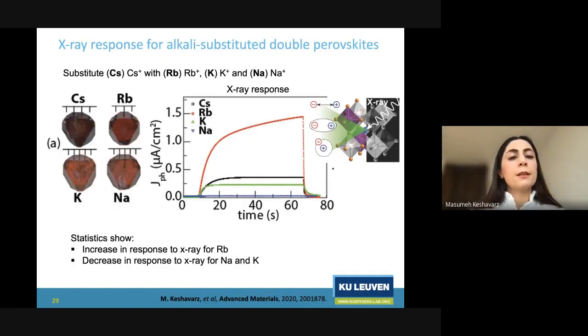Now, let's take the mother compound, which is the cesium silver bismuth bromide, and I emphasize, replace only 2% of cesium with rubidium, or potassium, or sodium. So upon this little substitution, one can see that the response upon X-ray exposure for the rubidium-substituted one is much larger than the mother compound, which is the black curve, as you can see here. So we succeeded to tune their properties by just substituting 2% of the cesium with rubidium.